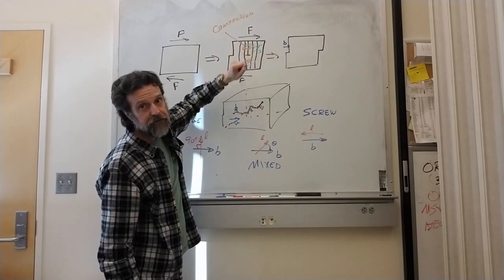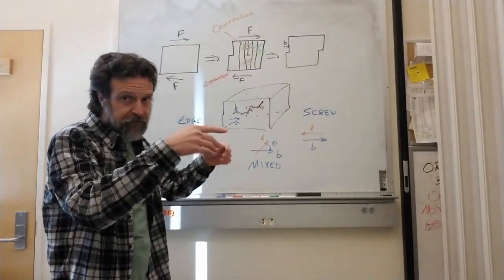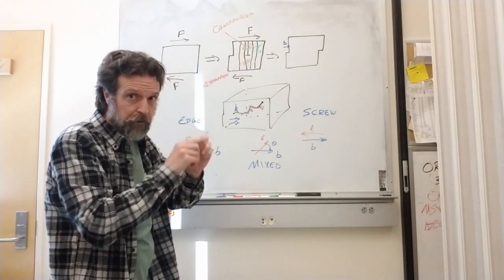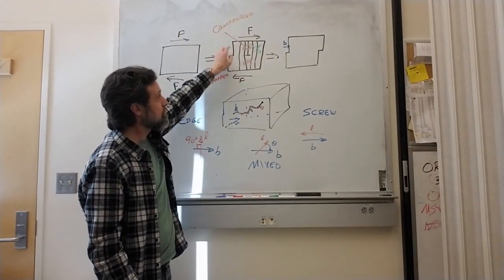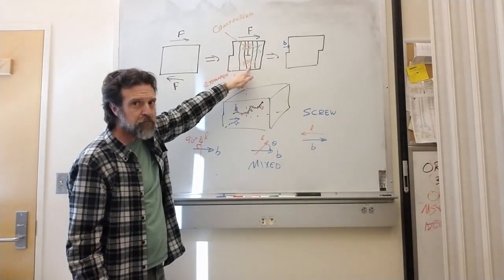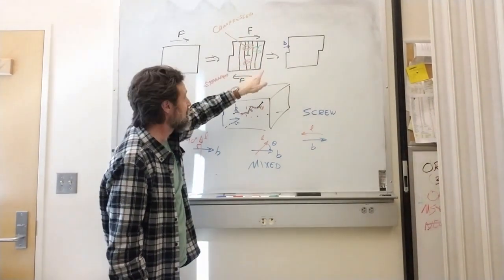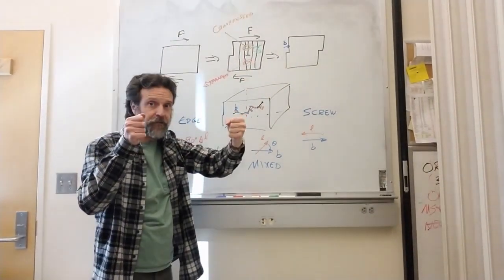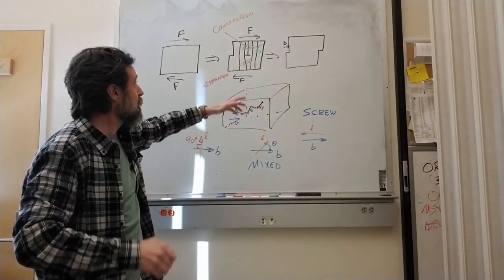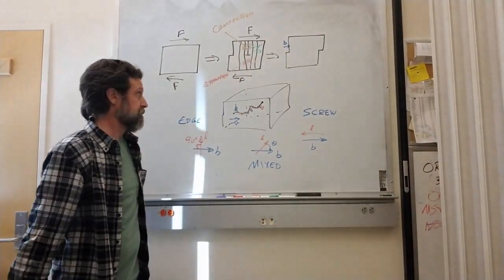The atoms sitting above the dislocation, because there's an extra plane, necessarily have bonds that are a little bit shorter. So these are all feeling compressed. Down here at the bottom, you could say we're missing half a plane of atoms instead of saying we have an extra one. These bonds are all stretched a little bit, therefore they are in tension. They're feeling a little bit expanded.